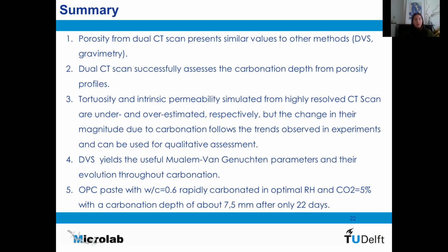Although the tortuosity and intrinsic permeability simulated from the highly resolved CT scans are under and overestimated respectively, the change in their magnitude due to carbonation follows the same trends observed in experiments in literature, and can be used for qualitative assessment. We also readily obtain the Mualem and Van Genuchten parameters and their evolution throughout carbonation.